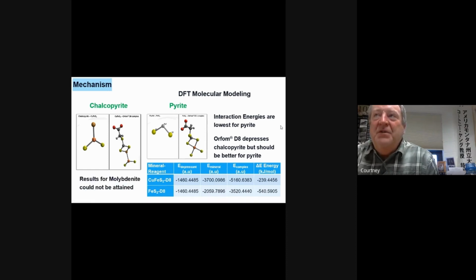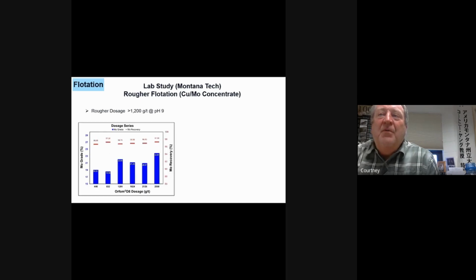And of course, once again, I'll repeat myself, results from molybdenite, we just could not attain them. Just wouldn't work. So let's go into the lab study then. Constraints here are our upper dosage is 1,200 grams per ton at pH 9. And this is the optimal dosage, or I should say a minimum dosage. But what we did was we changed the Orfom D8 dosage. That minimum is somewhere in here.